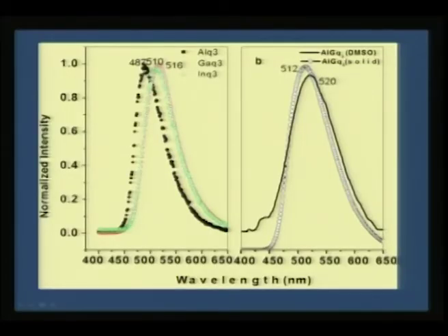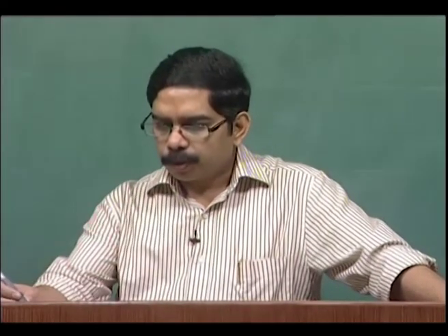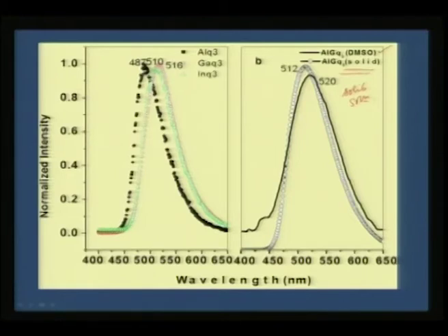You can clearly see that Alq3, Gaq3, Inq3 have preferred emission features, and if it is AlGaq3 in solid, it comes exactly between these solids, indicating that these are really solid solutions, and the solid solution seems to be very typical of its structure, and therefore you do not see much of a change whether you record it in solid or in liquid form.